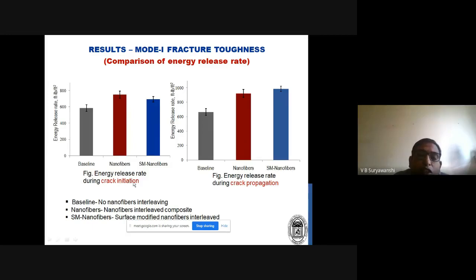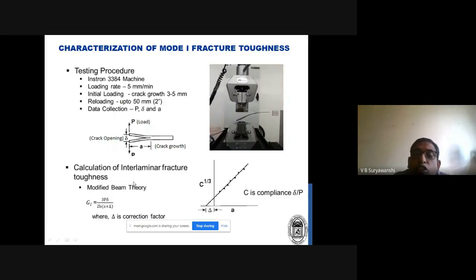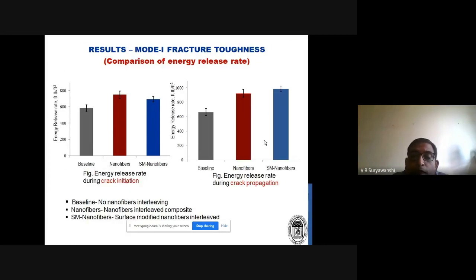So this is initiation. Initiation means when we just start pulling this, that is called the initiation stage. And the propagation is when the crack propagates. So at the initial level, we did not find any improvement in the case of the modified nanofibers. Whereas during the crack propagation, we found improvement in both cases. So this shows that if you use the nanofibers, we can improve the separation performance.